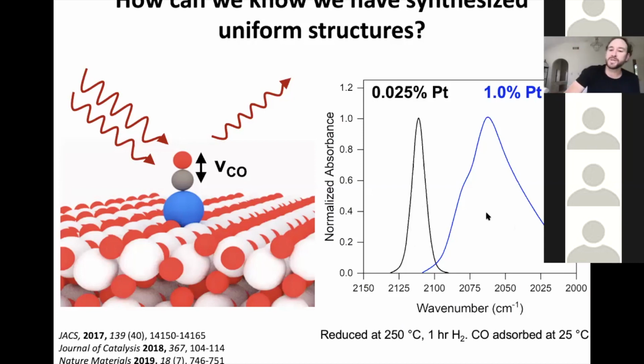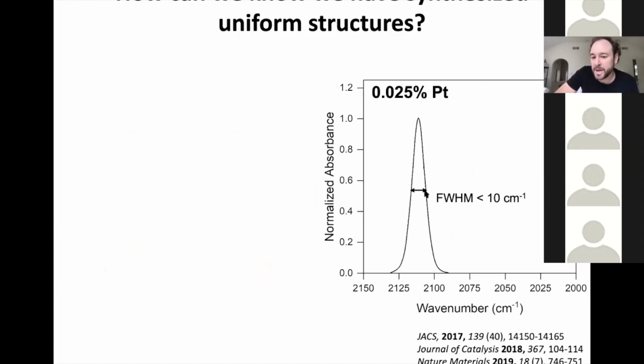So we can start to assess uniformity a little bit better by looking at bandwidths. If you took the full width at half maximum of this sample that we prepared here, where we think we have all single atoms from our microscopy, the bandwidth is a little bit less than 10 inverse centimeters.